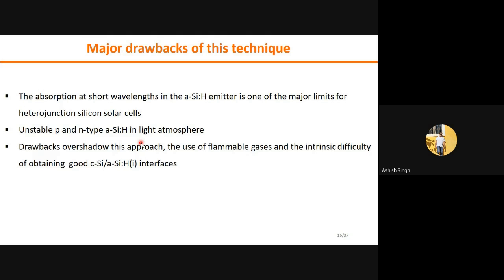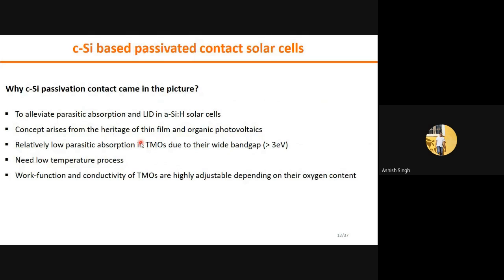In addition to this, one more important disadvantage: to make the amorphous silicon, we need to use pyrophoric and toxic gases, for example silane, phosphine, TMB, germane. These gases are really toxic and pyrophoric. So we need to make proper tubing to process with these gases. Thus, people started thinking about the same device architecture, which they called silicon-based passivated contact. In this device architecture, people use some oxide material for the hole and electron transport layer.